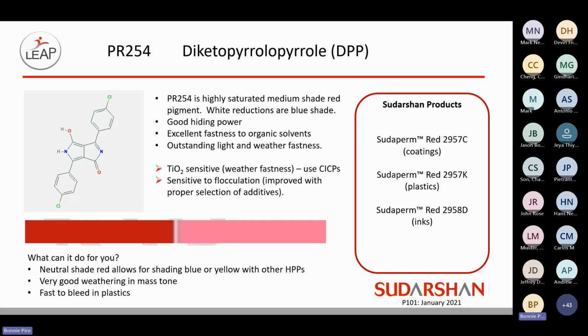The DPPs, the Pigment Red 254, is another workhorse in all application areas. It's a more mid-shade red. This one too, this chemistry is TiO2 sensitive. And also in liquid coatings, it can be sensitive to flocculation. So the proper selection of various additives can improve that particular property.